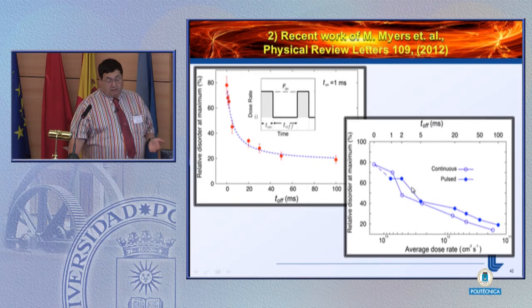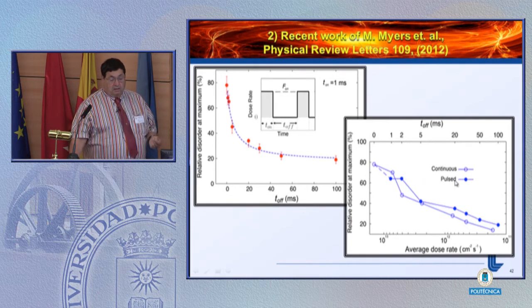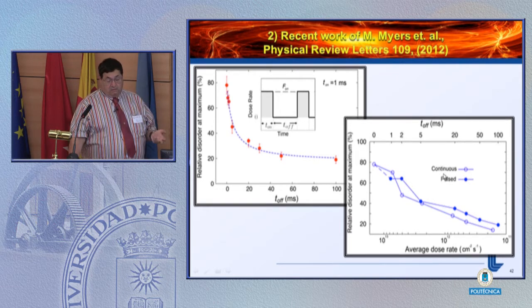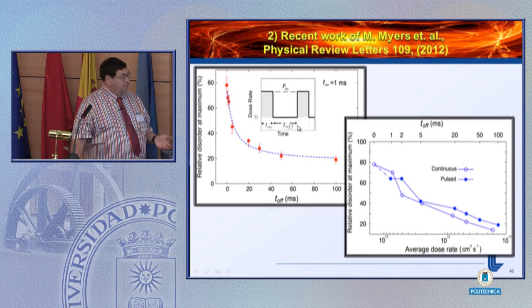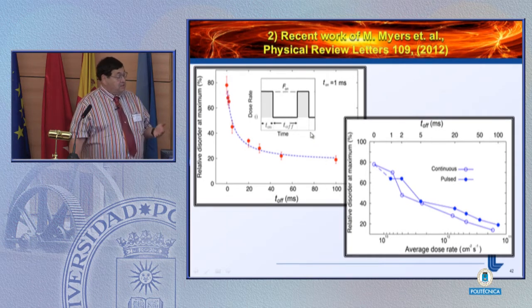So it turns out that pulse data, and this is the sort of insight that my colleague Sergey at Livermore had, basically imposes a time axis on the experiment and allows you then to extract kinetic data. Okay. Now that is very encouraging. That says we should be able to extrapolate, if you will, over 3 orders of magnitude by doing similar types of experiments on materials of technological interest in fusion energy.